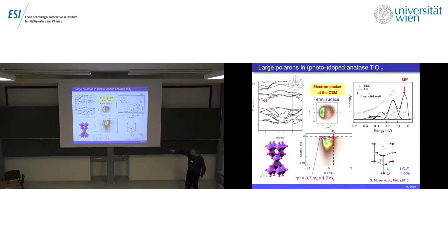And the spectrum measured at the Fermi momentum looks like this. This should remind you of the Franck-Condon problem for the molecule. There is a strong quasi-particle peak, but very clear, at least the first and the second satellite, and one can fit the spectrum with more satellites at the same distance, one from the other. And this distance corresponds to the energy of a longitudinal optical phonon mode. So we believe that this is an indication of the coupling of these electrons with this particular mode.